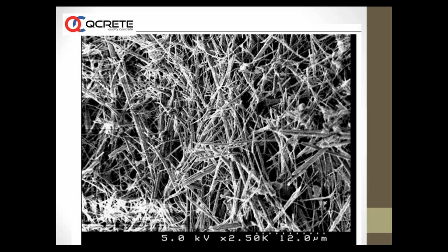Both materials, one used pre-construction along with the concrete production as an admixture, and the other used post-construction as a slurry or coating applied on top of virgin concrete, have become very popular. Manufacturers say the activation is continuous. The material penetrates up to about 50mm or 100mm and keeps reacting with the cement hydration products. As long as hydration continues, which can go on for 30-40 years as long as some moisture is present, this crystallization also keeps continuing, and the impermeability keeps improving.